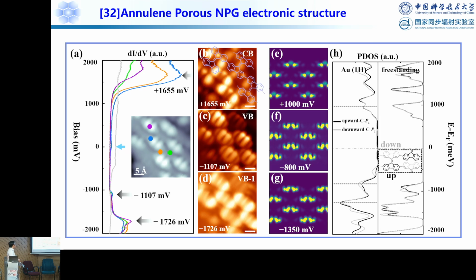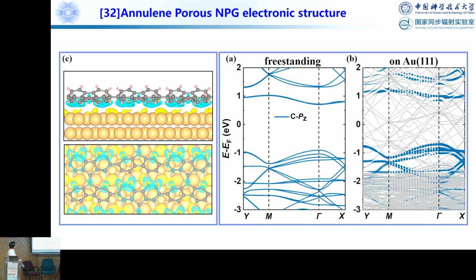Then with STS and dI/dV mapping, you can see the band gap. You can measure from here about 2.7, and in between here we have this small peak due to the interaction between the gold substrate and here. This is called a hybrid electron state near the Fermi edge. This is the calculated result, which tells that we do have some kind of interaction with the gold substrate. Again, this calculated result tells we have this hybrid electron state on the Au(111). Okay, I need to speed up.